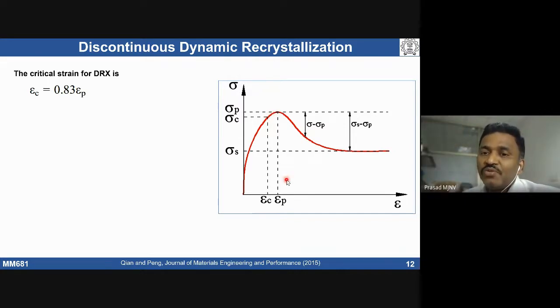Now we can know the degree of recrystallization without looking at the microstructure, based on this stress strain curve. I can estimate the degree of recrystallization and the volume fraction of recrystallization. So there are two things. People use the degree of recrystallization and the volume fraction of recrystallization just from stress strain data. Without looking into the microstructure, one can establish how much recrystallization is taking place. This is how people do it.